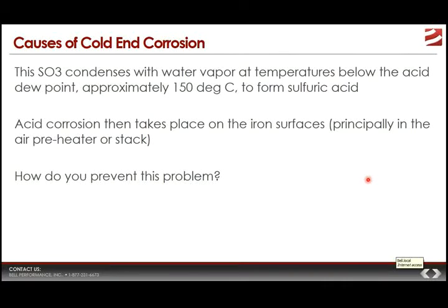So this SO3 is a problem because at some point later, it's going to find itself in proximity with water vapor. Remember, proper combustion yields carbon dioxide and water vapor. So there's going to be water vapor that this SO3 is going to be in proximity to. And at some point, it will combine, it will condense with it as it cools down and forms sulfuric acid. And then that sulfuric acid, if it reaches the right temperature, will condense out onto metal and iron surfaces, typically in colder areas like the air preheater or even the stack. And you get this really problematic cold end corrosion issue.